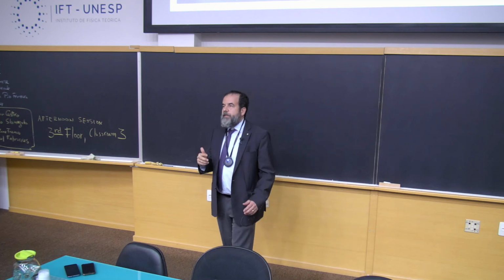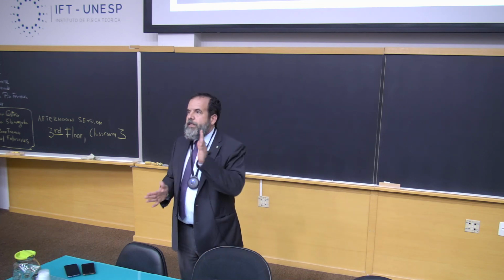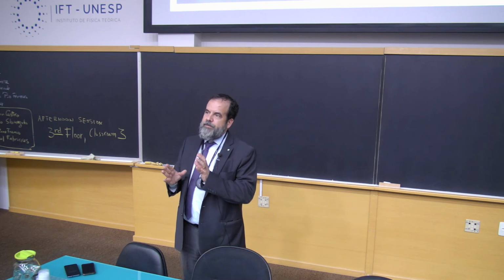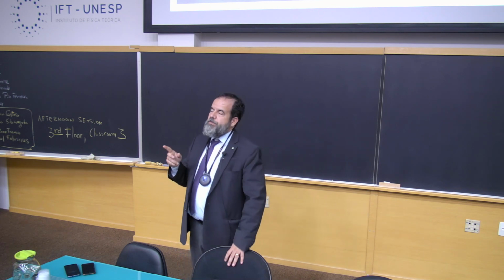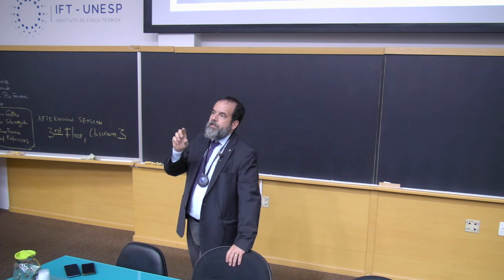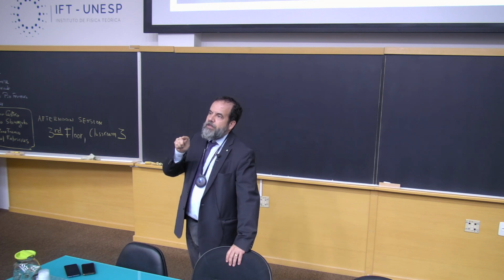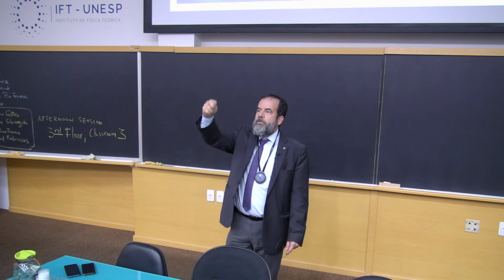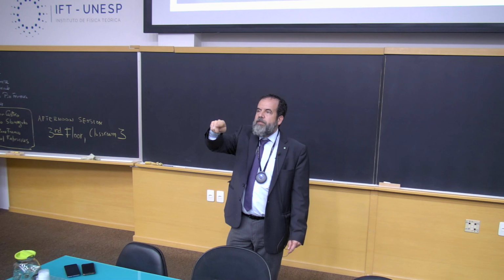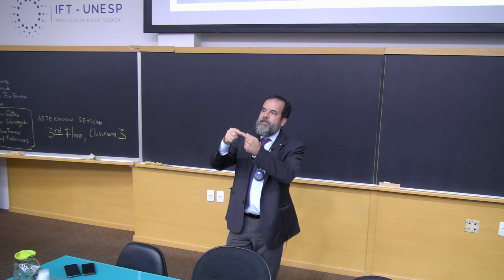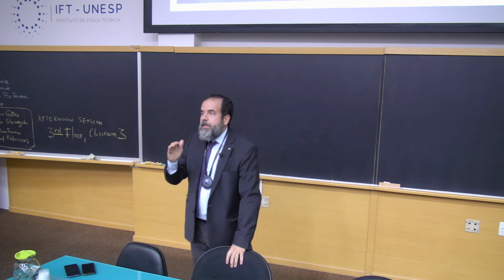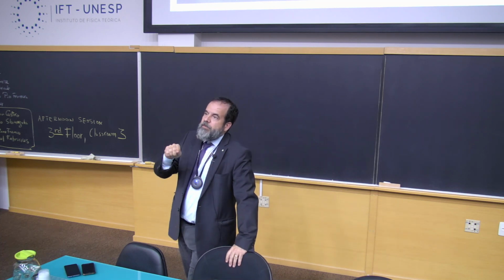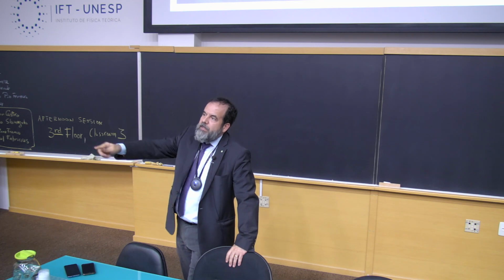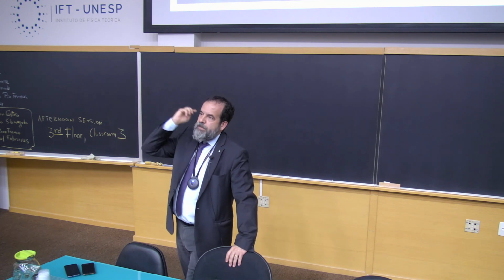Then the second point is that to make this separation of charges is not so obvious. And one of the main problems with materials like silicon is that if you don't have a perfect crystal, you have a lot of defects. And these defects will be responsible for what we call recombination. The charge won't reach the contact. It will basically recombine inside the silicon itself. So the more perfect you have, the less is the probability that you have this recombination. Then the efficiency will go up because these electrons will somehow reach the contacts.